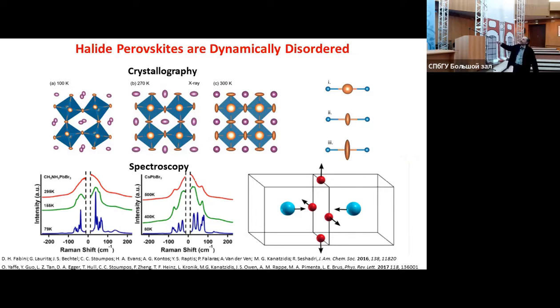That can be seen by the shrinking of the thermal ellipsoid by crystallography as we lower the temperature. This is normal, until you get a temperature that the atoms freeze and they finally are in the position you think they are. And the way to do this and prove it, because crystallographically this is impossible to do, we do Raman spectroscopy. And if you try to follow the Raman spectra, in this situation, the dynamically disordered situation, and this situation, you see that the Raman spectrum suddenly appears once the atoms freeze, and you have normal vibrations. And this is generic for either cesium or methylammonium, it doesn't matter. What changes is the temperature that you see this effect.